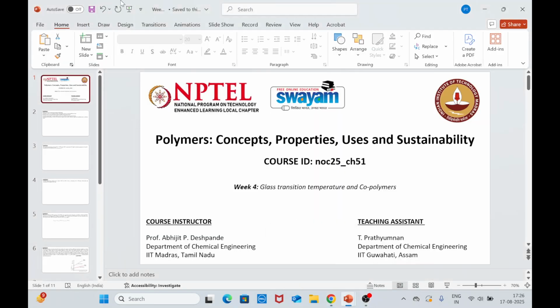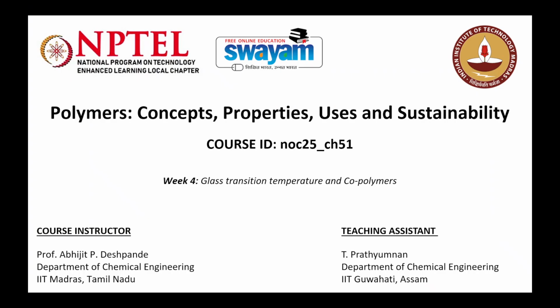Well, something very close you can say: since they cannot occupy the same site, there will be a space between these two segments, right? That empty space between the segments of the polymer is called the free volume. So the free volume will be more above Tg, and the free volume will be less at temperatures lower than Tg.